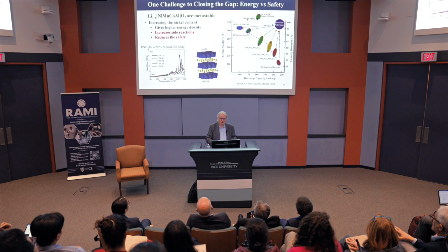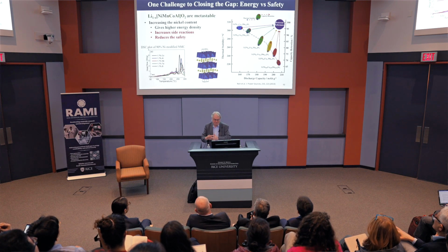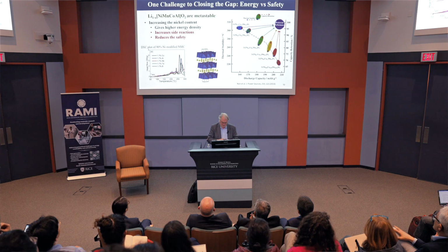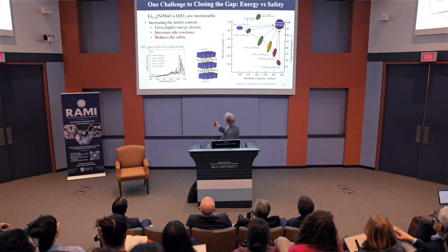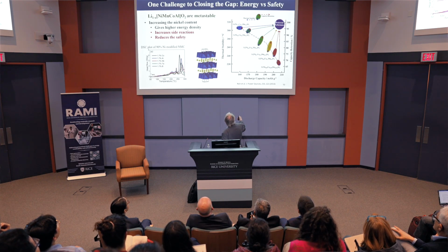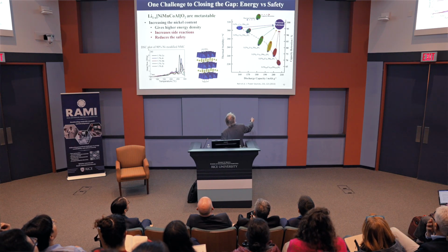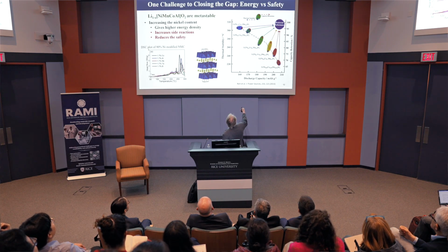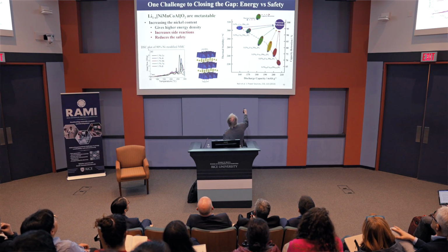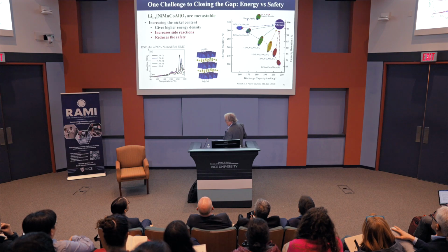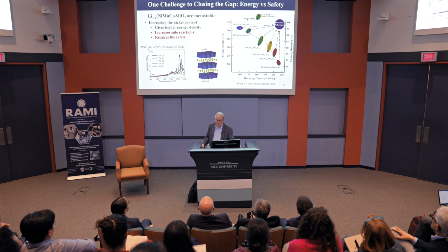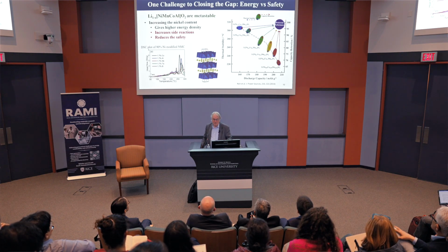So what is the issue? Why can't we have all nickel? This is a plot by South Korean folks, and maybe I can turn around and show you here. The energy or discharge capacity increases this way, and you see the nickel content is 50% or 30% here, up to 85%. So you get more and more energy, the more nickel you have in your system.